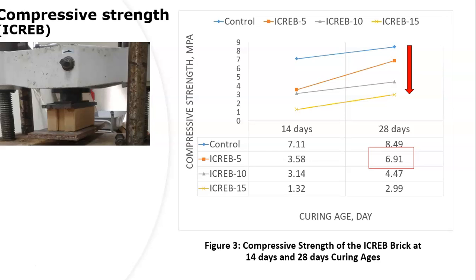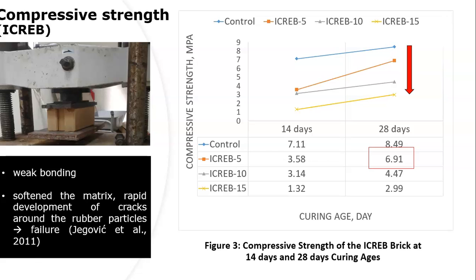28-day testing. And the decrease in the compressive strength of the rubberized interlocking brick was possibly due to weak bonding between the rubber particles and cement paste as compared to cement paste and natural aggregates or sand. On the other hand, the presence of rubber within the cement mortar phase has softened the matrix, hence rapid development of cracks around the rubber particles while loading leads to quick failure of the specimen.